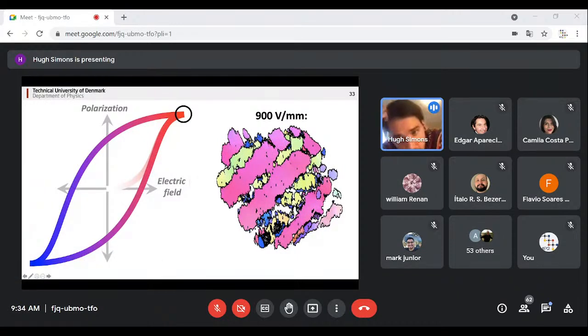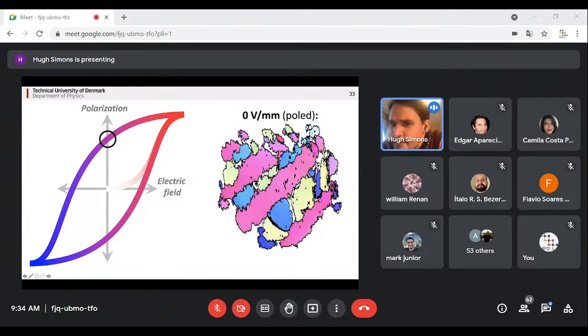And then as we remove the field, you would expect this poled structure to more or less remain where it is. And that's actually not what we saw. Well, there are some similarities, but the problem is that you form these new blue colored domains. And more worryingly, you form domain walls at oblique angles. Now, if they're classical ferroelectric domain walls, these should be at 90 degrees or 45 degrees. And this is really not at either of those. So you end up having domain walls at strange oblique angles. This is not energetically favorable, and it is a direct consequence of domain wall pinning from grain boundaries.